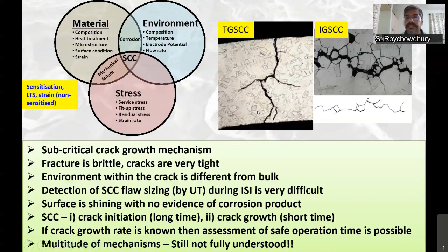SCC cracks are very tight, and all the corrosion processes are occurring at the crack tip, which is a few atoms in diameter. Detection of such tight cracks during in-service inspection is very, very difficult. Sizing of cracks is also very difficult. The surface which has undergone SCC is more or less free of any corrosion products. It will be shining, clean. So you do not have any telltale visual clues to indicate that some corrosion is occurring there.